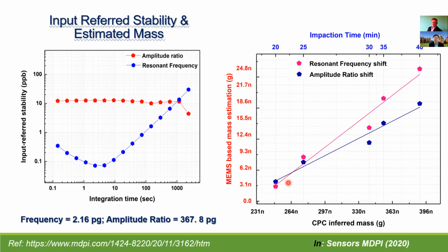And then by combining the previous sensitivity data and this stability data, the input referred stability was calculated. This input referred stability is calculated to obtain the minimum mass that can be sensed based on the frequency shift output metric, which is the traditional method, and the amplitude ratio shift output metric. So while observing the minimum mass that can be estimated based on the two output metrics, it was seen that the minimum mass that can be estimated based on frequency shift is 2.16 picogram and based on amplitude ratio is 367.8 picogram.